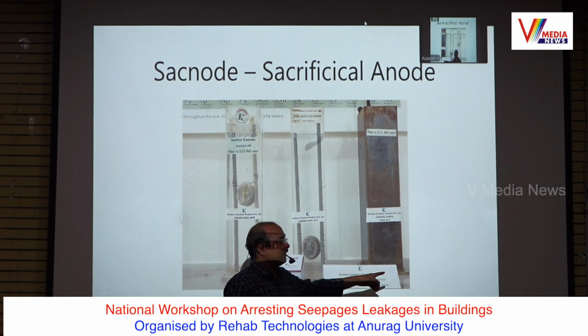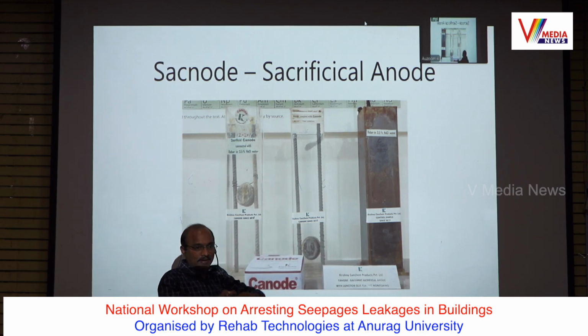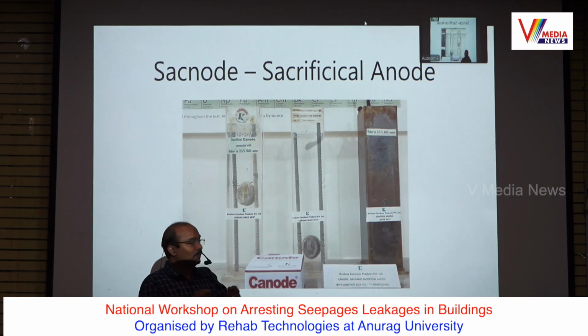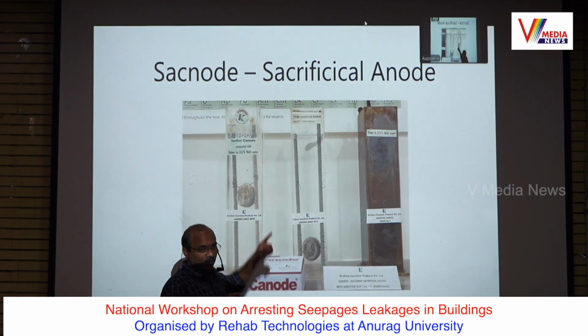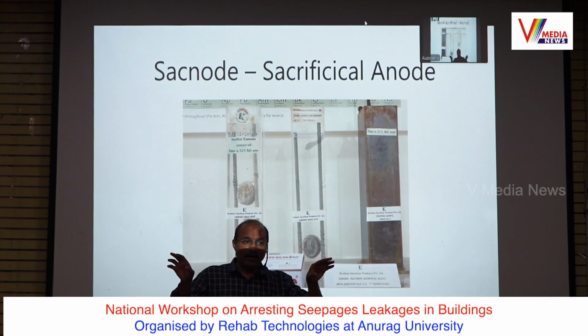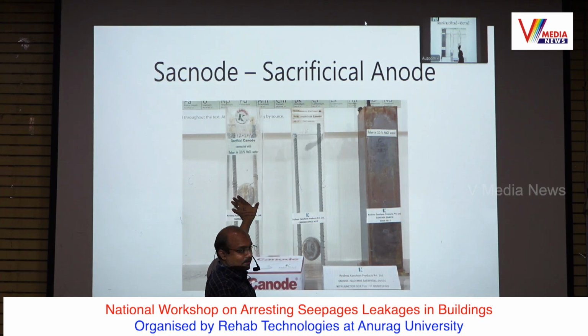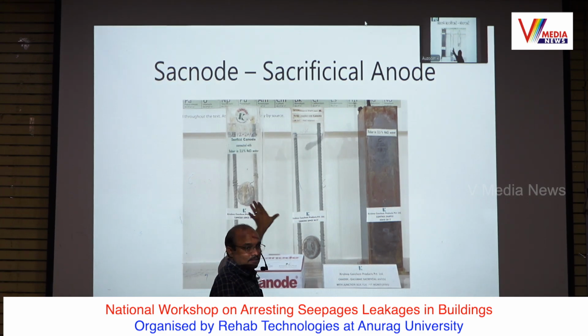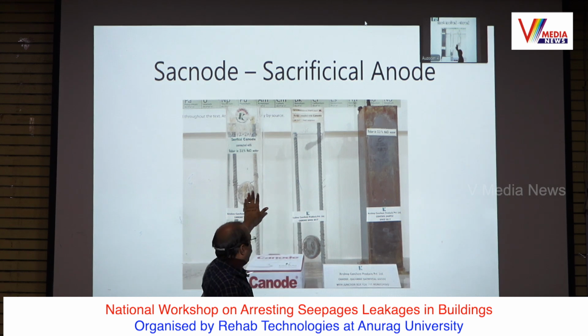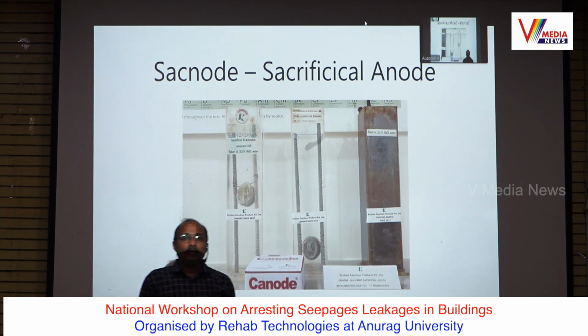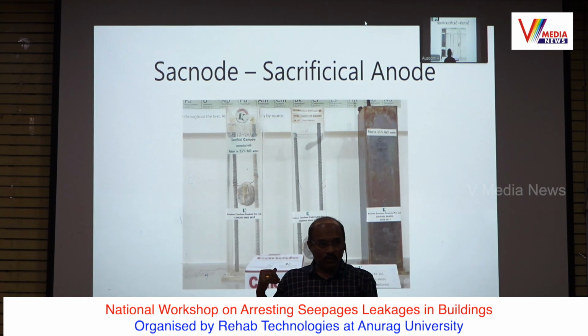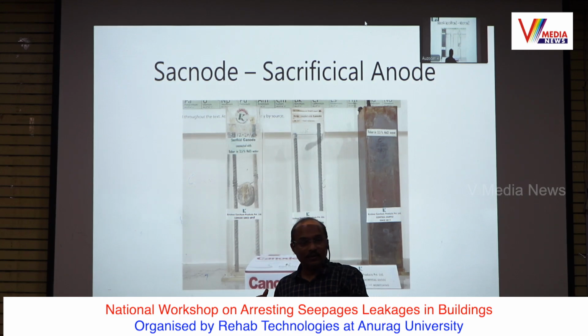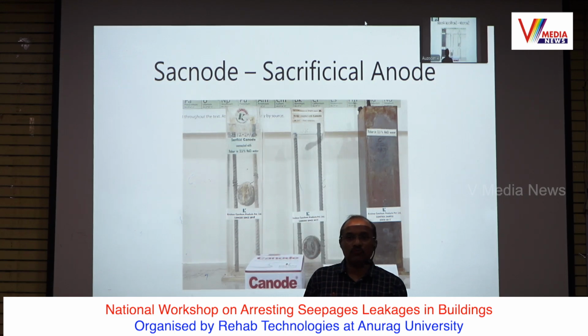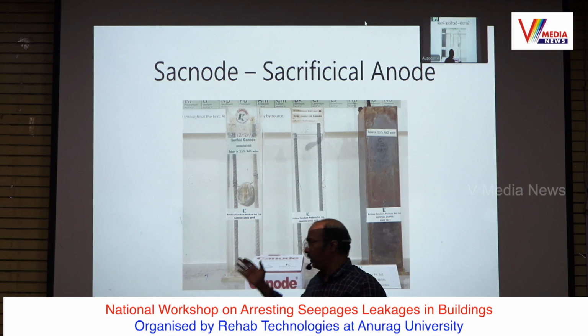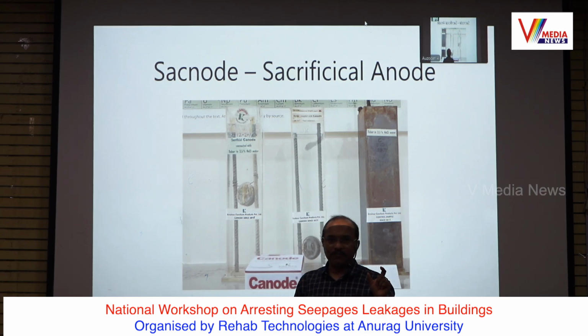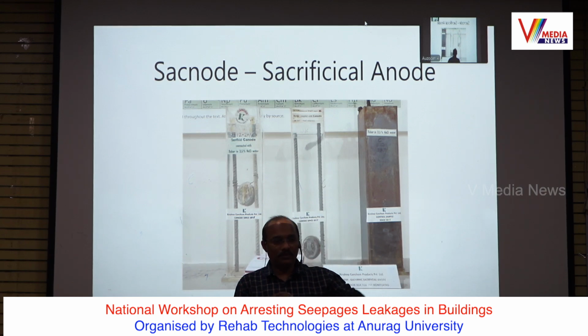So go for this kind of sacrificial anode, which is tied to a steel bar. This sacrificial anode will start emanating the required anodes to the steel, and the steel will take whatever is required from this rather than getting corroded. So what will this do? If the life of the concrete without this is something like 20 years, this will increase your life by 20 years. So 40 years is what you are absolutely assured of. And what will be the cost of it? 400-500 rupees, once, for the sacrificial anode. So you don't have to demolish your structure.